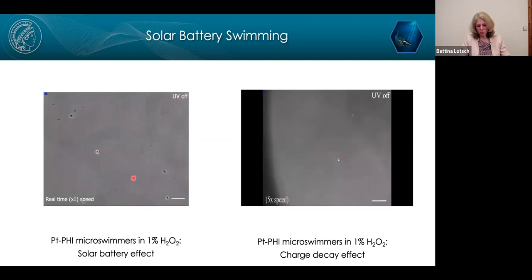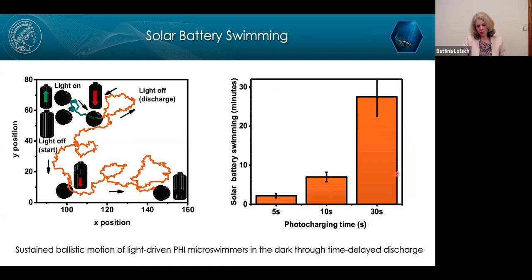This is shown perhaps even more clearly here, where we have the light on, and now we turn it off, and you see that there's a charge decay that goes on for a very long time. We turn off the light, and still the particle moves essentially ballistically. To put this into a graph, when we irradiate the system for 30 seconds, the particles move for up to about 30 minutes. This is a very interesting phenomenon that has never been observed before in these micron scale micro swimmers: we can charge up the system like a battery, then turn off the light and the particles continue to swim. We believe that is due to the slow but continuous release of electrons, taken up most likely by oxygen, as a source of continuous propulsion.